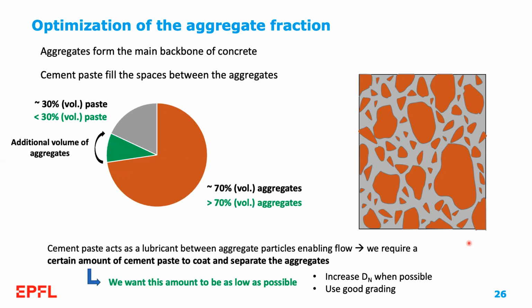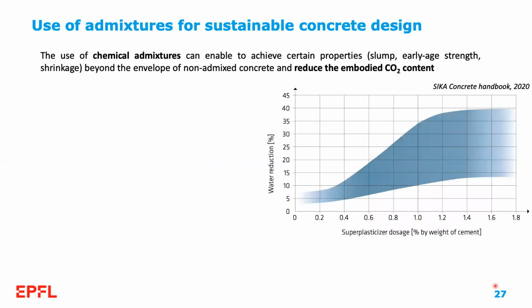In an ideal situation, what we would like to have is a concrete with more than 70% of aggregates and less than 30% of volume of cement paste. Chemical admixtures can enable us to achieve certain properties such as slump, early age strength, and shrinkage beyond the envelope of non-admixed concrete, and reduce the amount of embodied CO2. And I would like to illustrate this with an example with a superplasticizer.